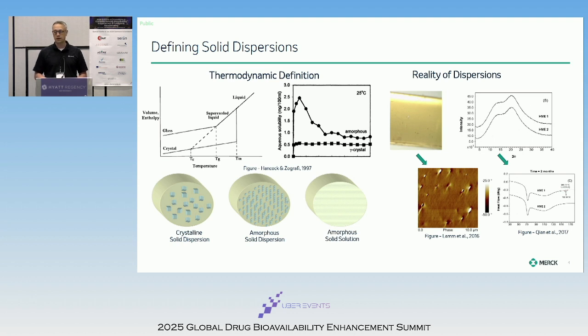So you could see an image of an extruded... Let's see if I can get to it. Right. So a little bit of a reach, but the extruded image in the upper left of those four panes is a clear glass coming out of the extruder, characteristic of what you would expect to see. When we go and actually look at this more closely under AFM, what we see is phase separation, and that's actually phase separation of the vitamin E TPGS.